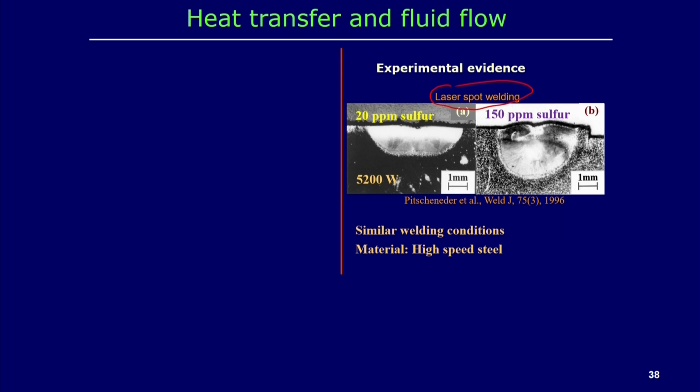So, in high speed steel with 20 ppm sulfur mixed in, the presence of 20 ppm sulfur produces this kind of profile, that means the depth of penetration is not high, the aspect ratio is very low, the width is very high and the depth of penetration is low. But in the presence of 150 ppm sulfur, for a similar material and similar welding conditions, that means similar laser power and laser spot diameter,